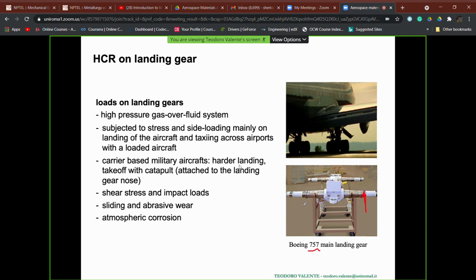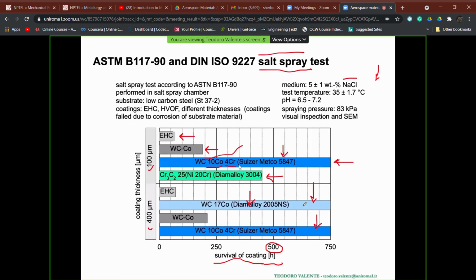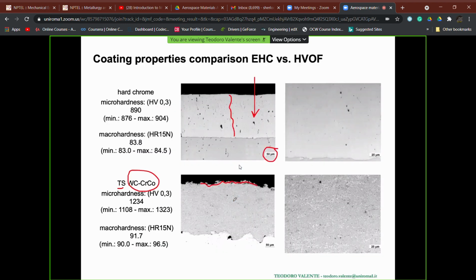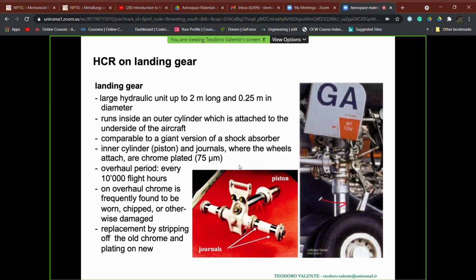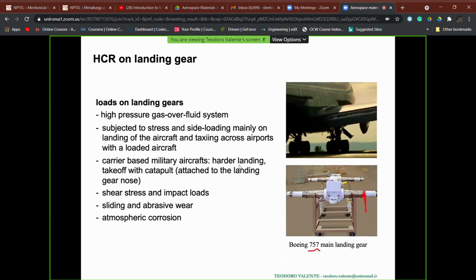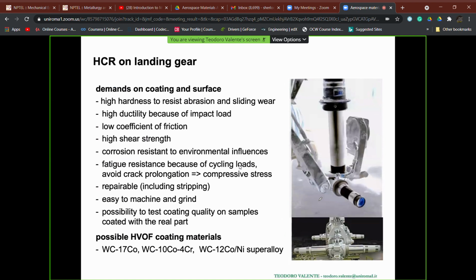The importance of HVOF in this case is related also to the fact that HVOF, as we said before, is a process driven by kinetic energy, so the coatings which can be fabricated, again have a look at this microstructure, are very dense, in a way which is comparable with those obtained by the standard hard chromium solution. So this is one field of application of HVOF related to the aircraft industries, which is very important for us.